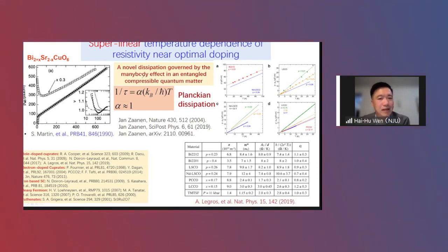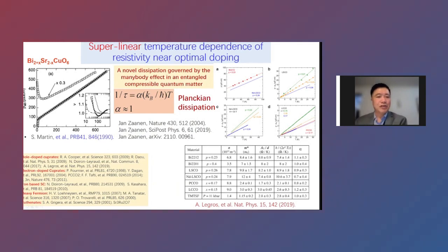And based on that data, several theorists, especially Subir Sachdev, proposed so-called novel dissipation governed by the many-body effect in these correlated systems. So in the entangled compressible quantum metal, it shows the scattering rate should be linear versus temperature with this kind of quantum number, okay? The alpha is close to 1. And this phenomenon has been found in many cuprates, and iron-based, heavy fermion systems, okay? And also in this paper, these people collected a lot of transport data to prove that indeed the alpha is quite close to 1. So that indeed shows such a behavior.